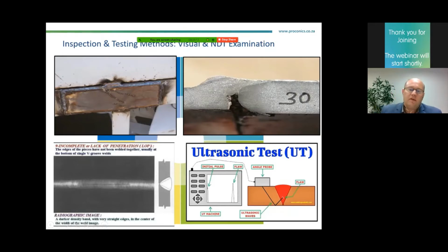To pick up these types of defects, you will have to conduct non-destructive testing. The two most commonly used methods to detect this defect are radiographic testing as well as ultrasonic testing. It all depends on the thickness of the material. So rework and retesting will have to be done on this weld. This means additional cost, which was not allowed for initially. For the rework, you will have to remove the weld, conduct NDE to ensure that you have sound metal again, re-weld, and then conduct the same method of non-destructive testing that you picked up the defect with initially.